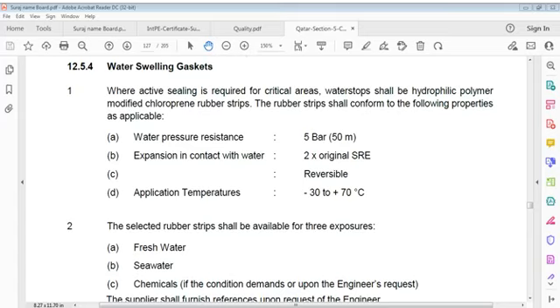Rubber strips shall conform to following properties as applicable: water pressure resistance 5 bar, 50 meters, and expansion in contact with water 2 times original size, reversible, application temperature minus 30 to plus 70. This is water swelling gasket.